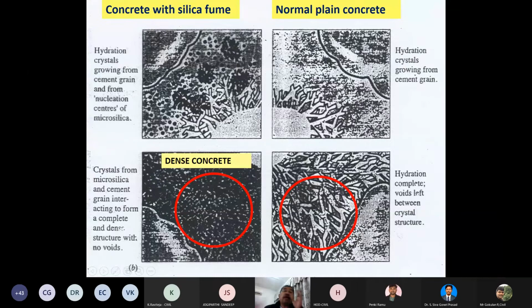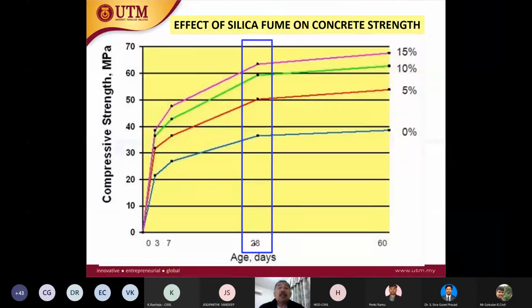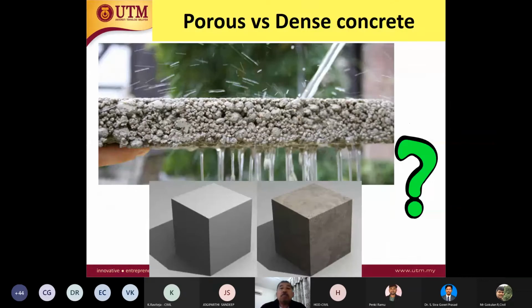So in order to increase the strength of the concrete, in order to make the concrete durable, less permeable, the concrete must be dense. So the idea to make the concrete dense is to use blended cement, which is a combination of OPC plus pozzolanic material. So this is an example. If we use silica fume, this is 0%, 5%, 10%. At 28 days, the strength increases. Why does strength increase? Because of the formation of more CSH gel, calcium silicate hydrate gel. So that is the concept.